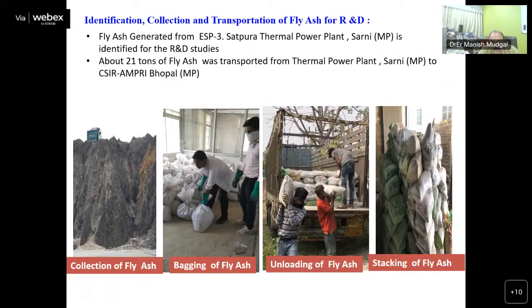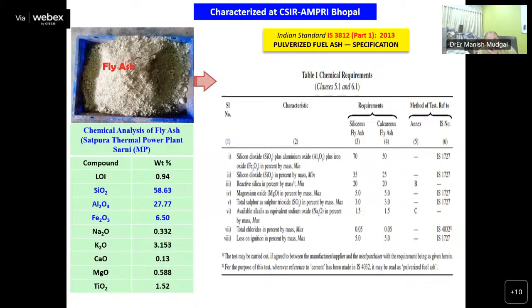I am working on bulk utilization of waste. That's why we have collected around 21 tons of fly ash from a nearby thermal power plant at Sarni, Government of MP thermal power plant. We have characterized this fly ash and found that it is a silico-aluminous material. Silica content is 58.63%, alumina 27.7%, and iron oxide is 6.5%.